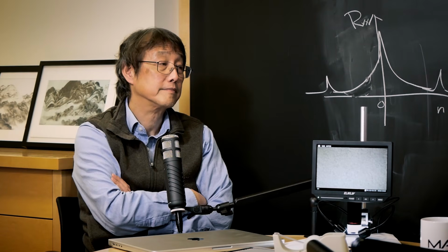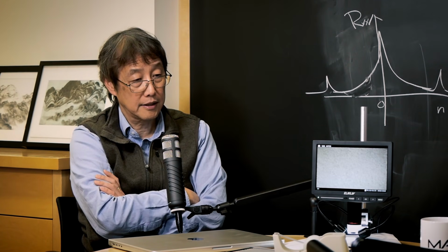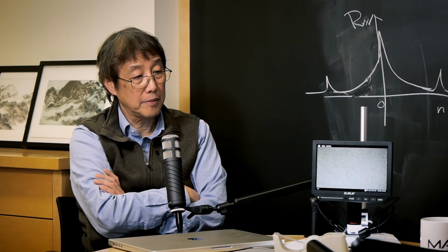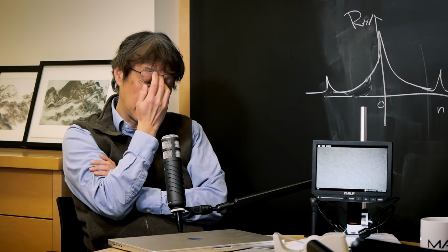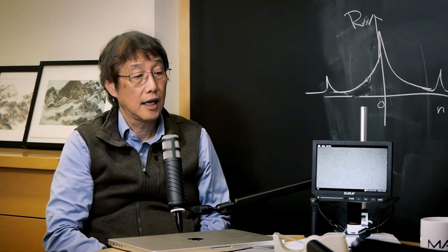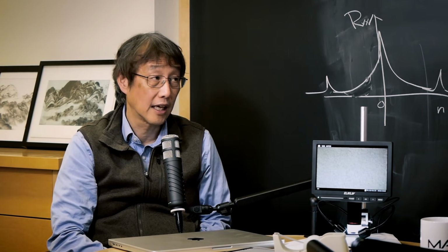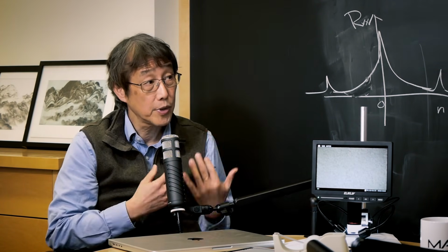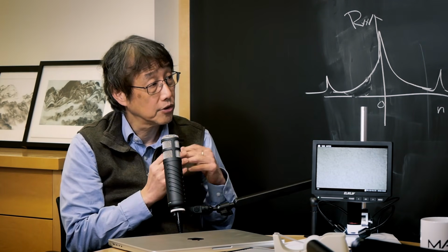Yeah. And what are the criteria for superconductivity in 2D materials, so this twisted angle structure? Right. I think one exciting part about this twistronics is the original demonstration. No one actually believed that graphene can produce superconductivity easily. Part of the reason is that for any superconductor, you need a relatively large density of states to get a higher Tc into the system. Now in graphene, because the carrier density is small, getting a large density of states is rather difficult. But by twisting it, you can make the flat band where you can engineer the large density of states. So that's one important ingredient to get superconductivity.